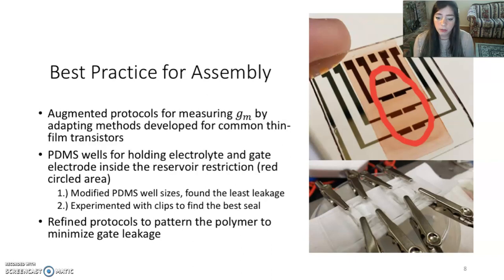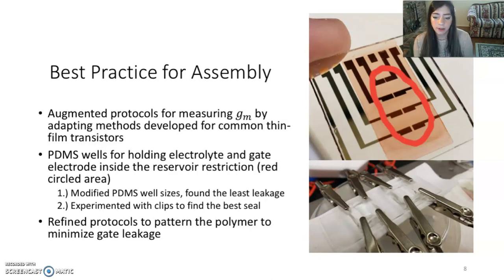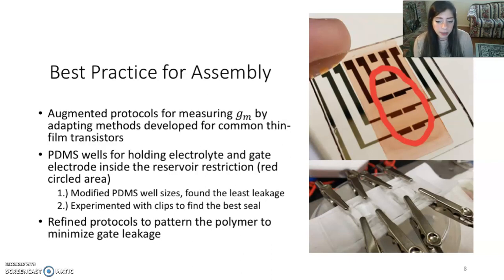We developed augmented protocols for measuring transconductance by testing out methods developed for thin film transistors and making them more suitable for our devices. We cut small wells out of PDMS to function as an electrolyte reservoir in the center of the chip. In the top image you can see the reservoir area restriction circled in red. The bottom image was taken during a series of experiments to improve the PDMS protocol by implementing clips to prevent leakage.